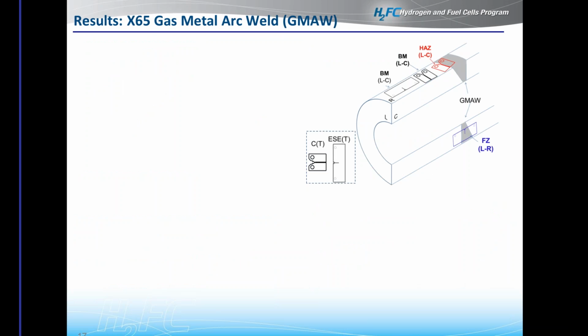So the results now of the X65 gas metal arc weld, as I mentioned, these schematics up here really just serve as a kind of legend for the fatigue crack growth curves. So we did test in the fusion zone. They also show what specimen geometry was tested for each condition. So in other words, we performed tests of the fusion zone here in blue, the heat affected zone in red, and then of the base metal in black.